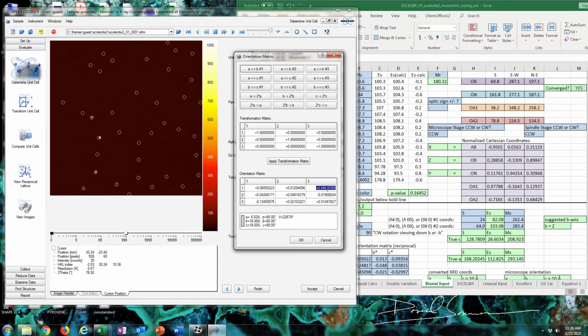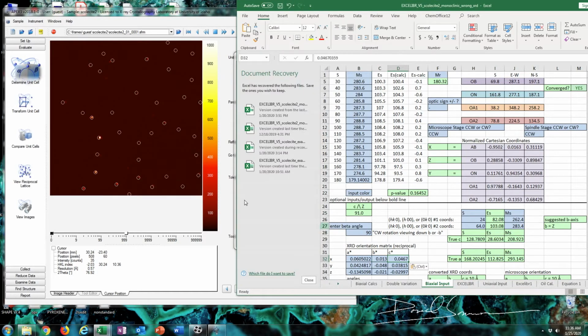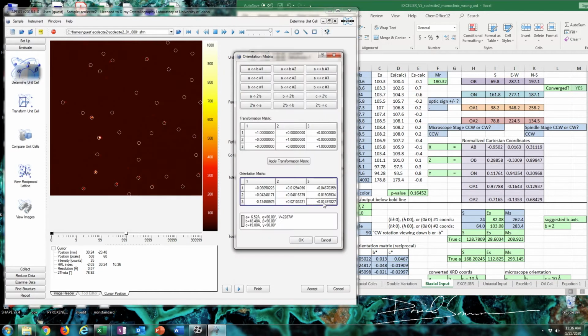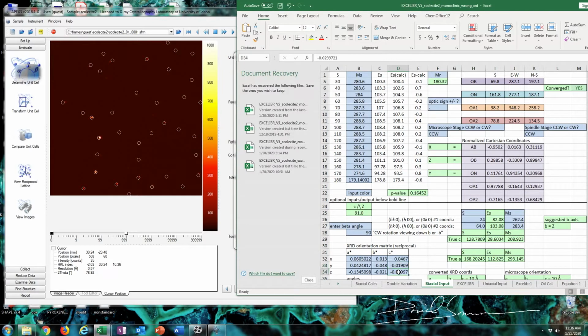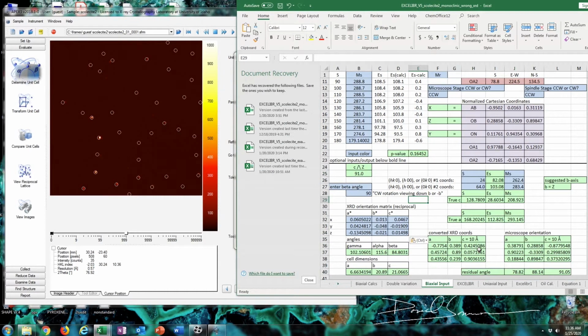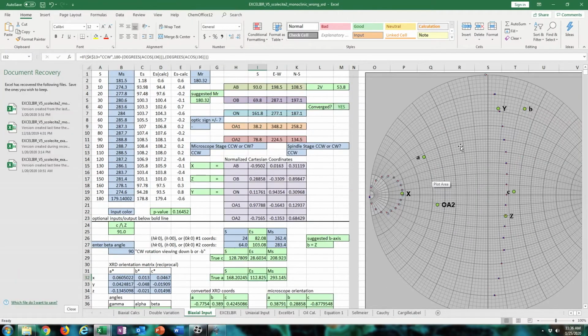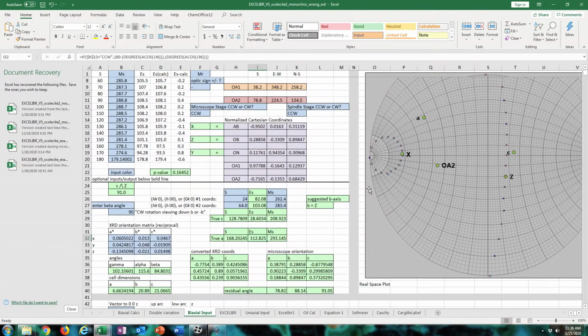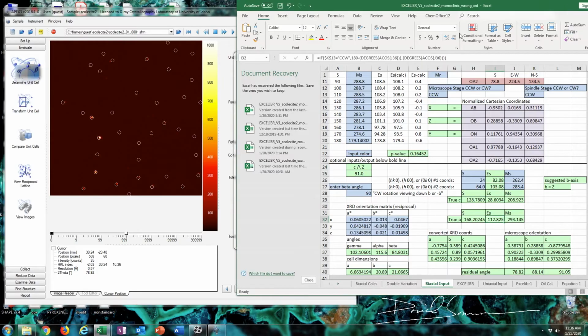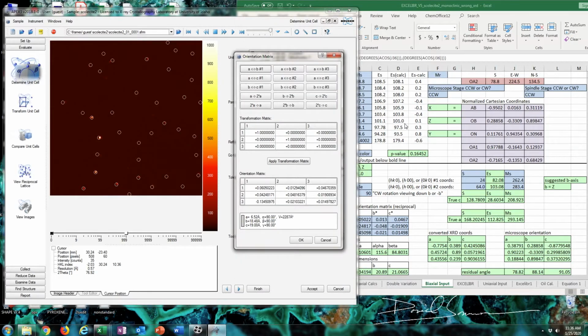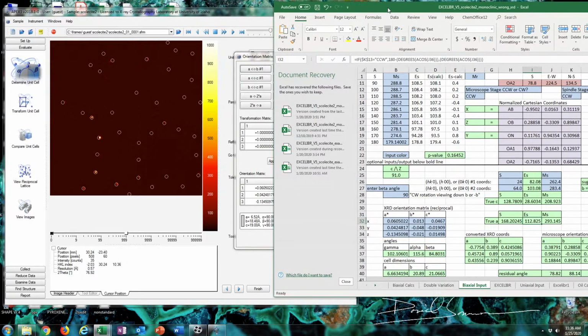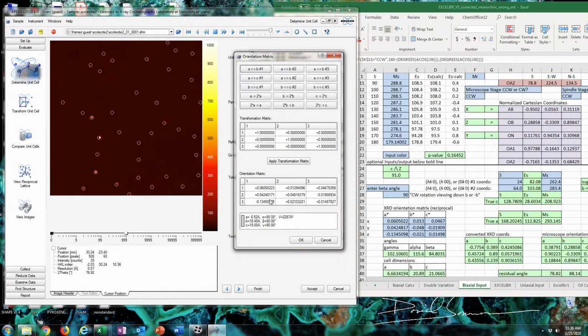And the C axis can either be 108 degrees away from A and normal to B in one direction or the other. It just so happens that 108 degrees either way has very similar translational characteristics for scolecite. So you can get mixed up with that too, and I've had that happen on here with this example.